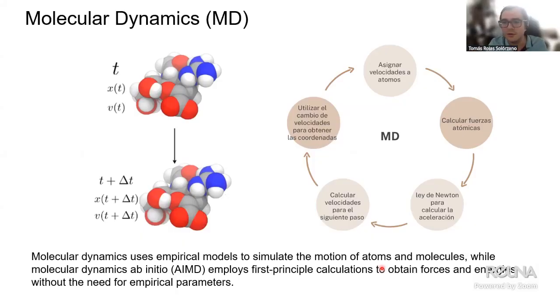Again, the drawback is that it's a much more complex calculation, and that makes it more difficult to run a larger system or to run the system for longer. So typically in ab initio molecular dynamics, we run it on the scale of picoseconds. It could be between 5 and 20 picoseconds, those are typical values. And the systems are typically on the scale of tens, sometimes maybe hundreds of angstroms in size. So it's another tool. Later on, I'll speak briefly on a methodology we have been using right now to merge both of them, using the pros of both of these methodologies.